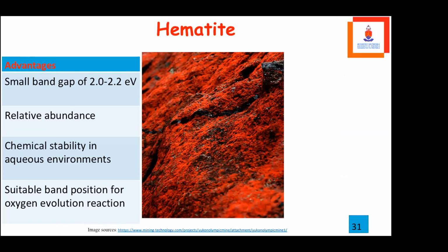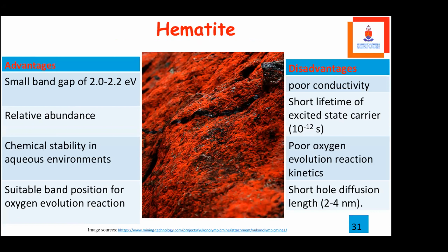So when we look at iron oxide, hematite, the advantage is that it has that small band gap, is relatively abundant, therefore it is cheaper to use, it's chemically stable in aqueous environments, and it has a suitable position for oxygen evolution reaction. And the disadvantages are that it is a poor conductor of electricity. It has a short lifetime of excited carrier charges, poor oxygen evolution reaction kinetics, and a very short diffusion length. And what happens with the very short diffusion length is that when electron hole pairs are created, they will recombine very quickly.